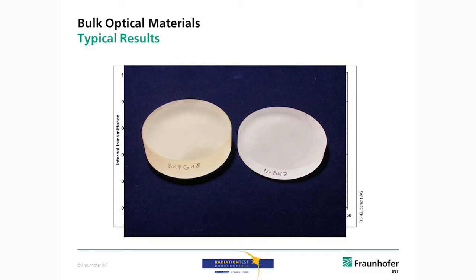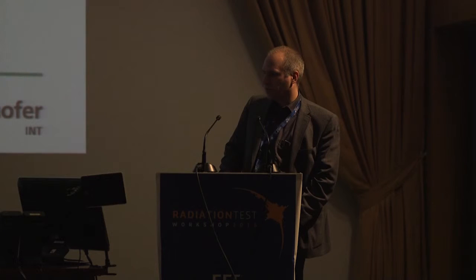And here's an example of a typical test setup we use, where you can put the samples in here. We use the light source coming from a fiber, which widens the beam, passing through the sample, and then getting on an optical spectrum analyzer to get the transmission spectra.